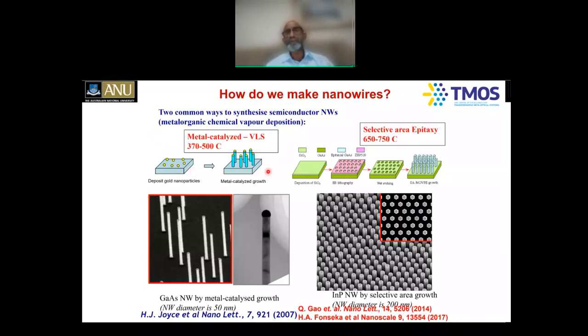If you introduce the gases needed for the growth of gallium arsenide in this case, trimethyl gallium and arsine, these gases get incorporated into the liquid alloy, it gets supersaturated, and crystals start precipitating out. You can get beautiful gallium arsenide nanowires, cylindrically shaped with no tapering. The transmission electron microscope image has also shown us that they're atomically perfect. The diameter of the nanowire is essentially determined by the diameter of the nanoparticle you use. In this case, we used a 50 nanometer nanoparticle, and you can see the gold nanoparticle on the top, and here is the gallium arsenide nanowire. This work is, in fact, by my former student, Dr. Hannah Joyce, during her PhD, and now she's an associate professor at Cambridge University.